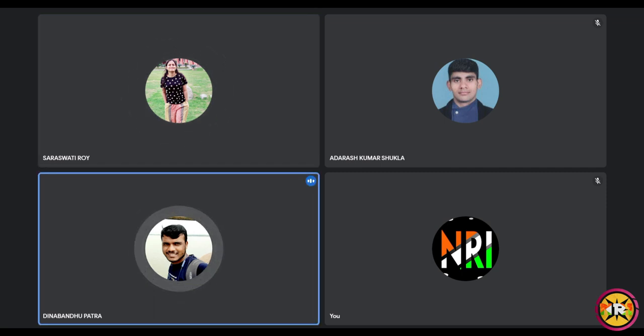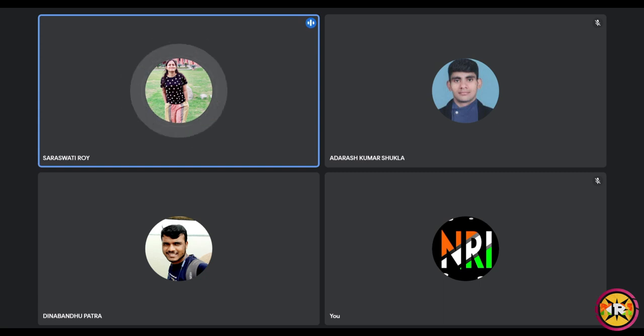And your electrochemical surface area is more for SCS than the other synthesized samples, right? Yes. So which role is dominating here, surface area or oxygen vacancy? See, for a catalyst, like for OER, there are so many descriptors, not only oxygen vacancy. Oxygen vacancy is one descriptor, and as we all know, if you have a higher surface area, then the catalyst will show higher catalytic activity. So for that reason, we can say the catalytic activity of SCS is higher.